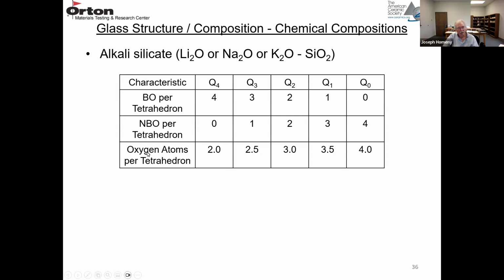And then you can calculate the oxygen atoms per tetrahedron. In this case, Q4, you have 4 bridging oxygens, so you're going to have 2 oxygens per tetrahedron. And then the other extreme, Q0, no bridging oxygens, 4 non-bridging oxygens, so you're going to have 4 oxygens per tetrahedron. And then these in between, Q3 is 2.5, Q2 is 3, and Q1 is 3.5.